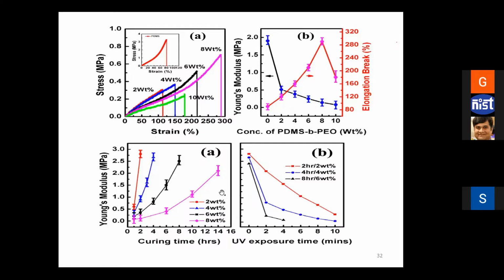We tried to come up with different weight percentages of PDMS-b-PEO such that it can have a very high stretchability with respect to stress and strain. We tested different concentrations of PDMS-b-PEO and saw how its Young's modulus changes. Then how its curing time changes, because time is important. In how much time, and how do different weight percents of PDMS-b-PEO affect its Young's modulus? How does UV exposure affect it, because we have kept benzophenone, which is a light sensitive material.